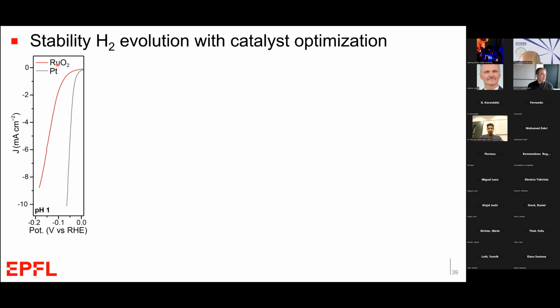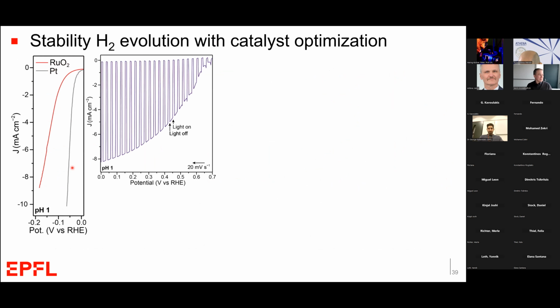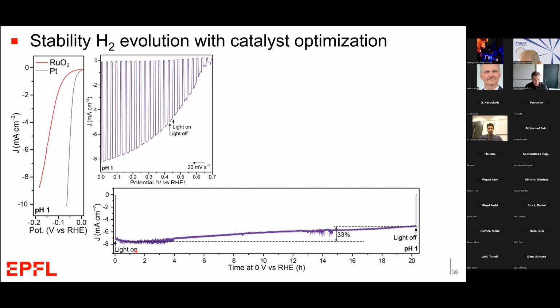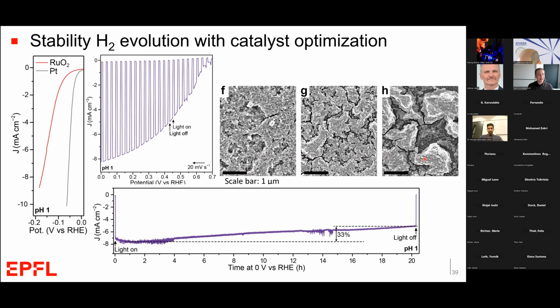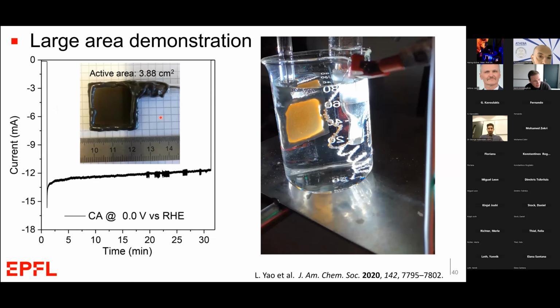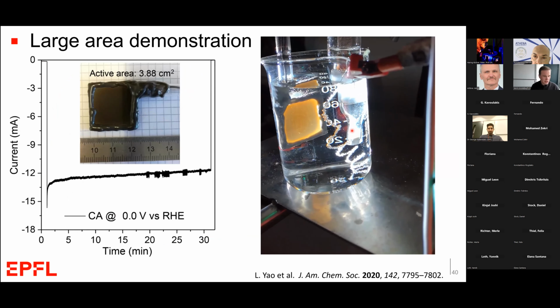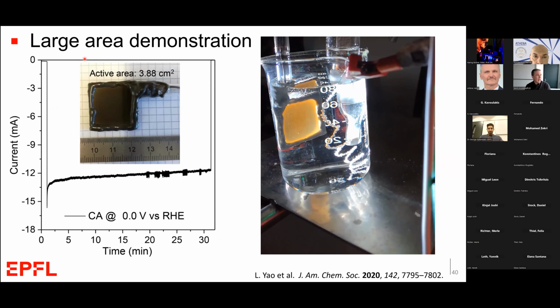We've achieved the best results with this ruthenium oxide-based HER catalyst, which has a better adhesion compared to platinum on the surface. And overall, we've achieved quite good stability for about a day, only losing 33% of the initial photocurrent of the photocathode. And that's still probably due to some of the catalyst layer falling off, as shown here on the SEM. But overall, this performance is quite nice for a photocathode. And we can do this over a large area. We can make simply solution processed photocathodes, which can make hydrogen here under illumination with an applied bias with these organic based light absorbers.